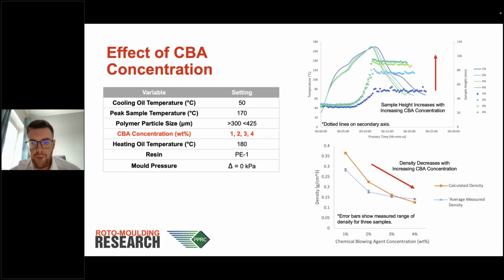So I've got a couple of examples to demonstrate what that shows. In this case, it's the effect of chemical blowing agent concentration, which is a fairly standard thing to adjust to get a thicker foam. And you can see on the graph here that there's barely any change during the first 5 minutes. Towards 10 minutes then there's a dramatic increase in the foam height, and that increasing percentage of blowing agent gives you an increase in the foam height.